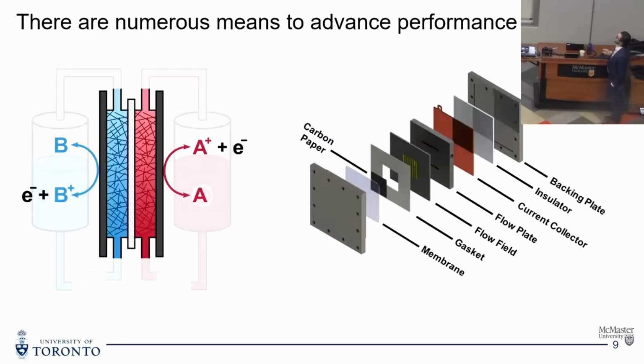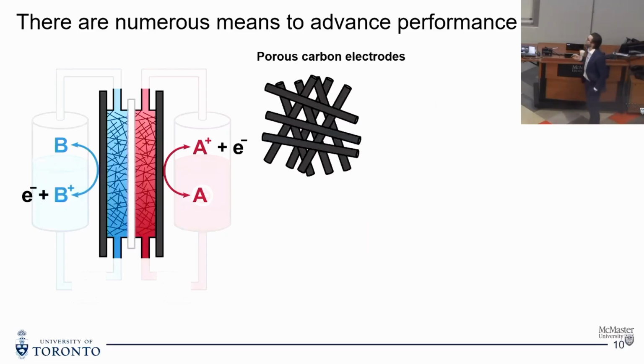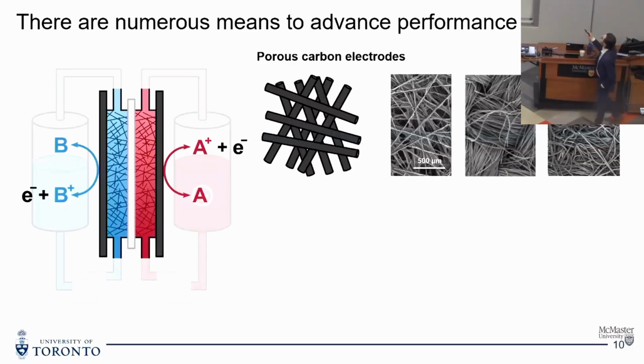These reactions in our reactor take place at some porous carbon electrodes. Typically, these are something with high surface area that allow for high mass transport rates and fast kinetics for our reacting materials. These can be carbon cloths, carbon felts, and carbon papers, essentially interwoven bundles of carbon fibers that give us high surface area and are conductive for doing electrochemical reactions.